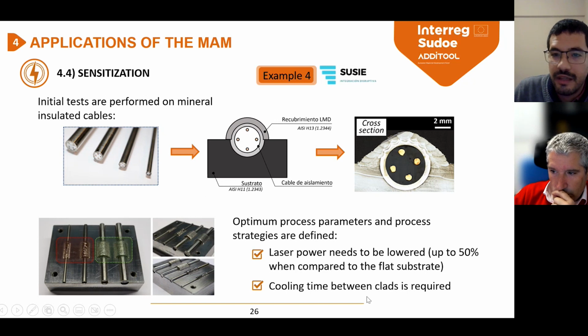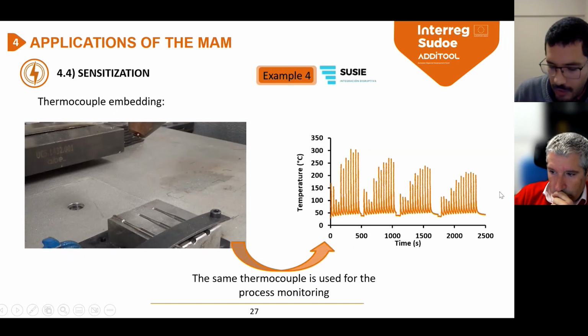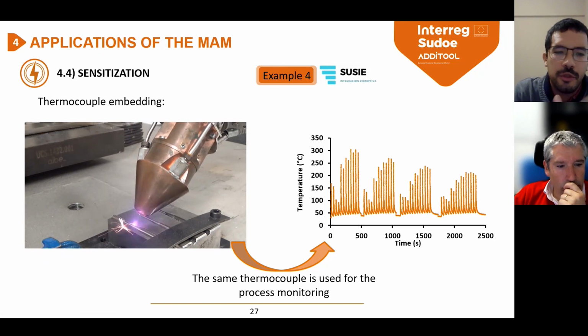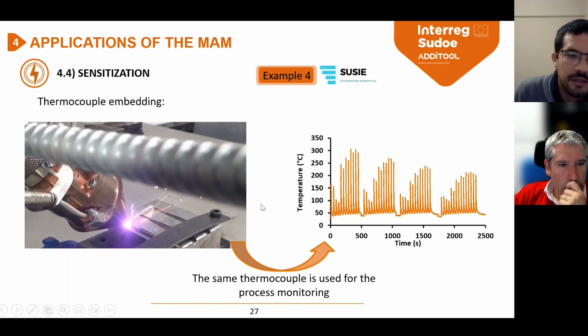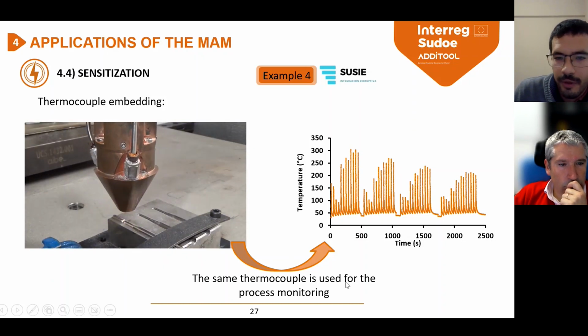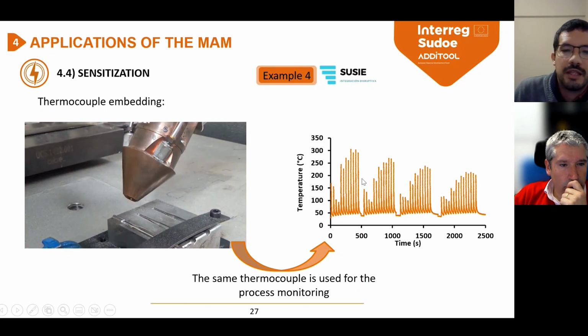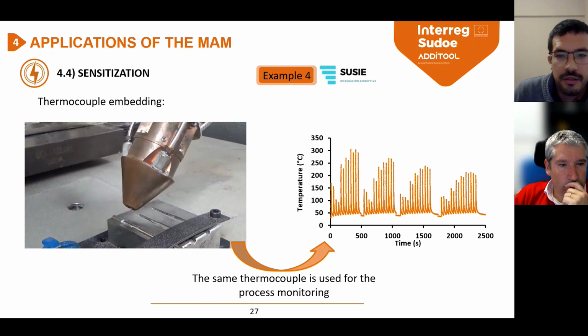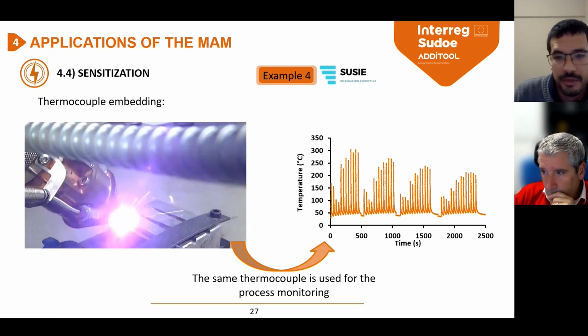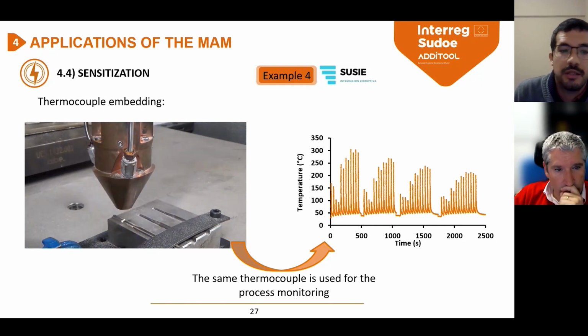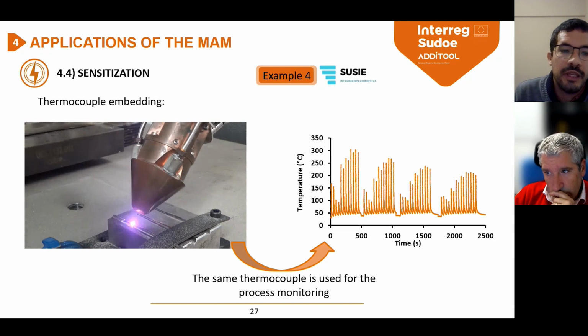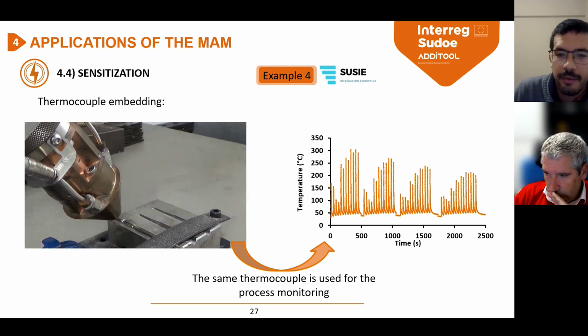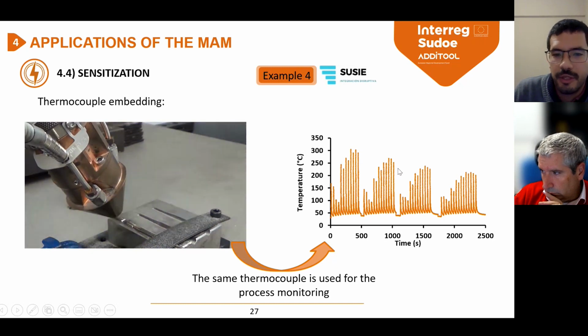And also, in order to stabilize the process, because heat dissipation in the thermocouple is rather small, we need to include cooling time between the different clad deposition. Luckily, we can also use the same thermocouple for monitoring the process. And as you can see in this video, while we are depositing material on the thermocouple, we measure the temperature, and somehow we obtain two benefits. On the one hand, we can control the cooling time, so we know when to start depositing the next line. And on the other hand, if we damage the thermocouple, we will also notice that on the temperature measurement.